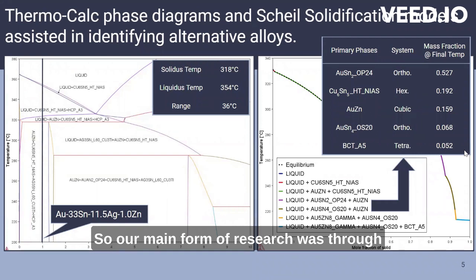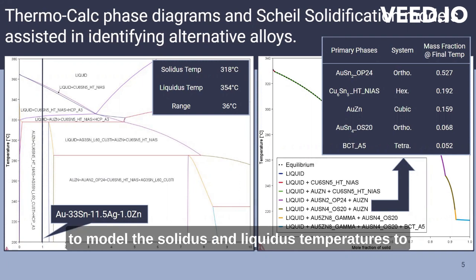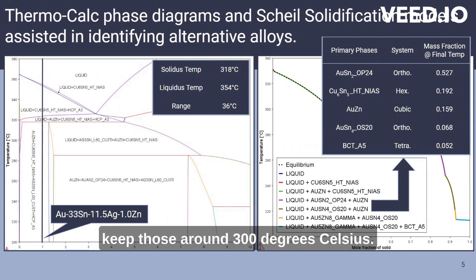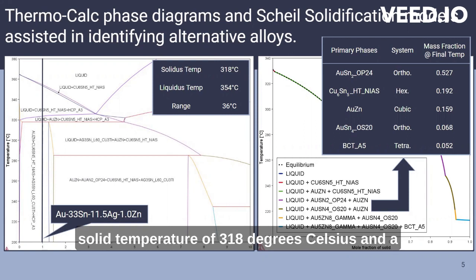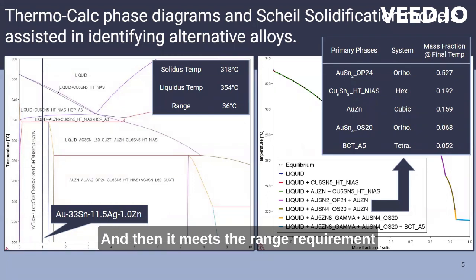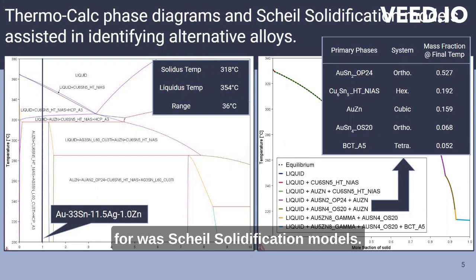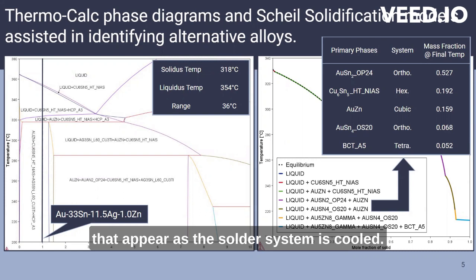So our main form of research was through Thermo-Calc, and the main use of this was to model the solidus and liquidus temperatures to keep those around 300 degrees Celsius. In this example here, the system has a solidus temperature of 318 degrees Celsius and a liquidus temperature of 354 degrees Celsius. And it meets the range requirement of under 50 degrees Celsius as well. Then the other thing we used Thermo-Calc for was Scheil solidification models. And what this shows you is the phases that appear as the solder system is cooled.